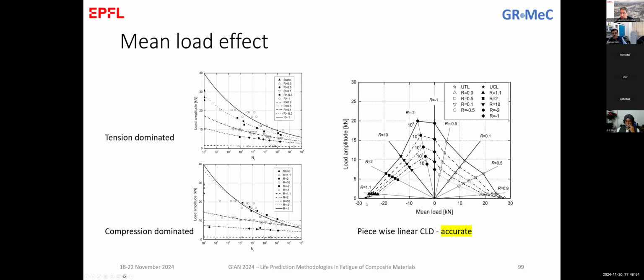Coming back to the discussion that we had before, regions that are closer to R equal to 1, so these regions and these regions, are regions where we have creep-dominated fatigue. Regions that are around 0.1 or 10 are more fatigue-dominated fatigue. And this is the case where we have reverse loading, plus and minus at 0. Theoretically, this is a case where we have alternating loads above and below 0 mean stress. Theoretically, this is the pure fatigue condition, where we have a 0 mean stress.